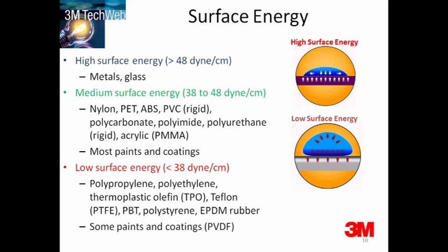Substrate surfaces can be defined by their surface energy. Those below 38 dynes per centimetre are traditionally difficult to bond to. Surface energy is a complex phenomenon that can also be divided into polar and non-polar components. But for the purpose of today's talk, we'll keep it at the top level. Surface energy helps us understand intermolecular attraction.